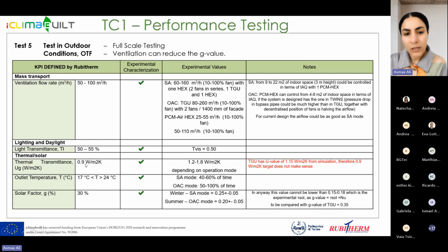However, we defined 0.9, but using the simulations, this was found not realistic, because the simulation of such a configuration was in the range of 1.15. So this also depends on the operation mode. The outlet temperatures that were defined between 17 to 25 degrees Celsius were achieved between 40 to 60% of the time in supply air mode, and 50 to 100% of the time in outdoor air curtain mode.